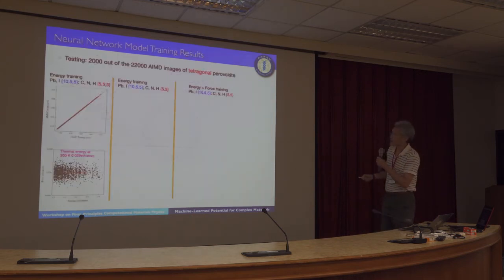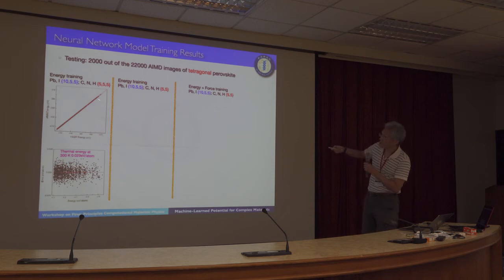And here's the training results. As you can see for the training set, for training setting 1, the horizontal axis is the energies from VASP, and the vertical axis is the energy predicted from the neural network models. You can find that they basically lie on this diagonal line with a very small error. So this is much smaller than the thermal energy at 300K.